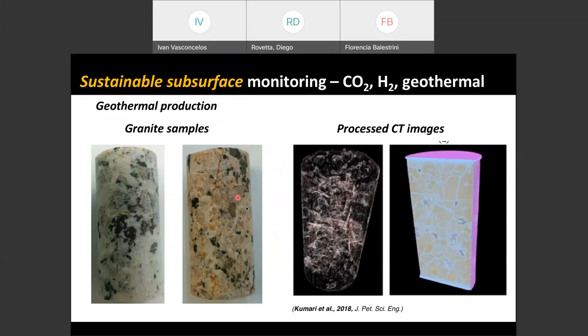But in fact, if you look at the CT here, so this is before, and it shows you the voids before, and this is after, and the after is showing you cracks in blue, and in light gray here, it's showing you an increase in microporosity throughout the entire sample. So the sample got more porous, and the sample got more brittle because of these cracks. And we would like to know that this is happening because it could be associated, for example, with subsidence or with the risk of microseismicity. So would we be able to get any of this information is the question.